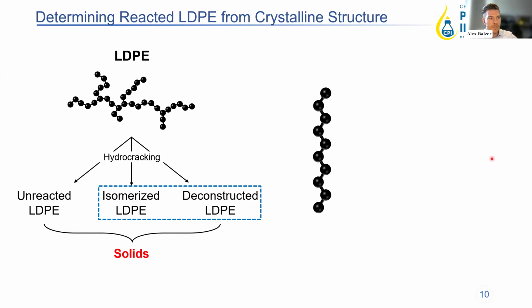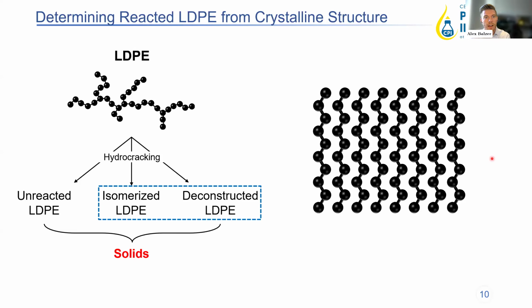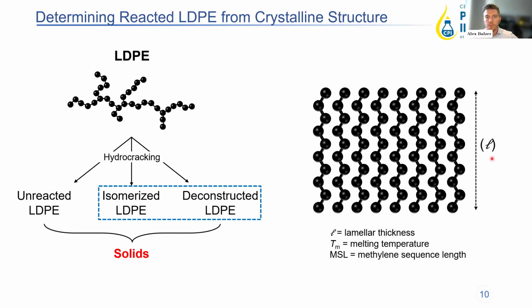And the way we can understand this is through the crystalline structure of our solids after the deconstruction. If we look at how a polyethylene crystallizes, you get one chain that starts to line up with several more, and the length that the backbone crystallizes in is called the lamellar thickness, which is generally related to the melting temperature of the crystal. And if we wanted to see how large of a crystal we can make, in the case of low density polyethylenes, the largest crystal you can make is limited by how far apart your branches are. That's because once you introduce a branch into this polymer chain, it effectively acts as a defect in your crystal. And that limits how large of a crystal you can make.